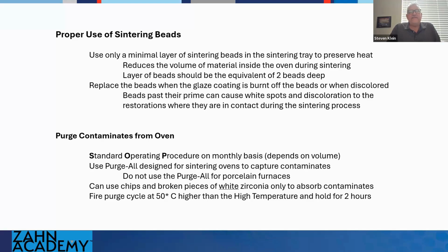Purging contaminants from the oven. This is also something that should become part of your standard operating procedure on a monthly basis. Of course, that depends on volume, but a good first of the month or end of the month, whatever date you pick, you should plan on purging your ovens on a periodic basis. Even these multi-layered zirconias, all of them have those chromas. You're not staining and dipping, but those can get expelled out into the furnace and can cause discoloration and shades being off. So just plan on purging at least on a monthly basis.